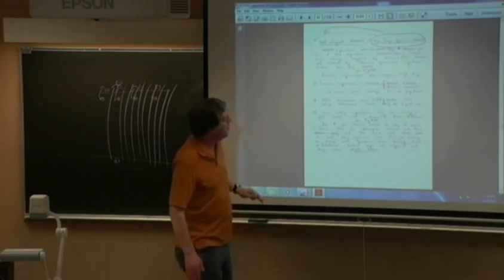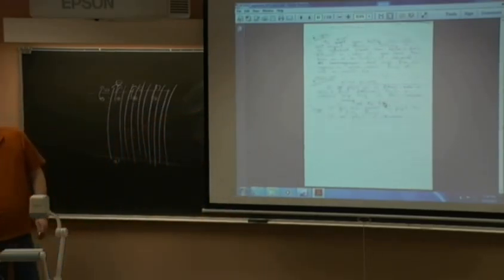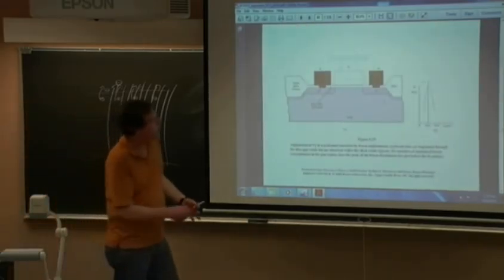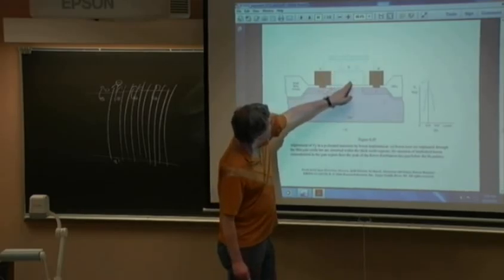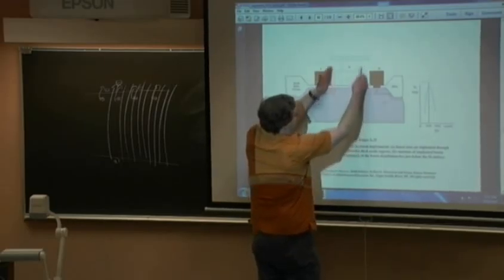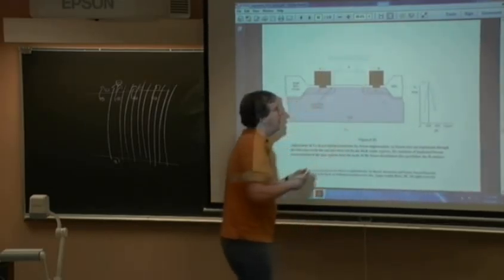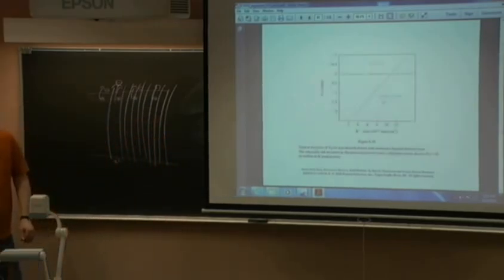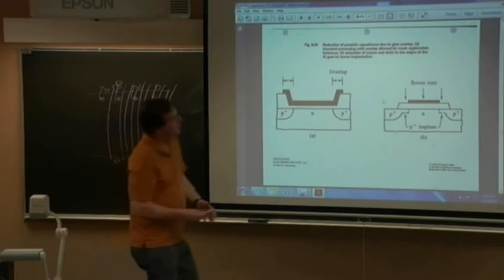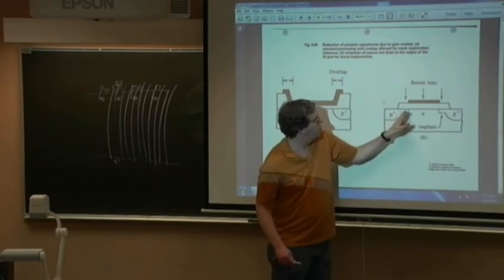The self-aligned MOSFET: ion implantation is used, and the polysilicon gate acts as a marker — the implantation follows the sidewall of the gate. It becomes self-aligned. This not only changes threshold voltage but creates a beautiful self-aligned transistor where source and drain are perfectly indexed to the gate, avoiding excess overlap capacitance.